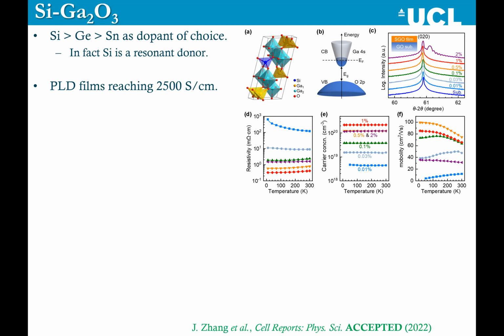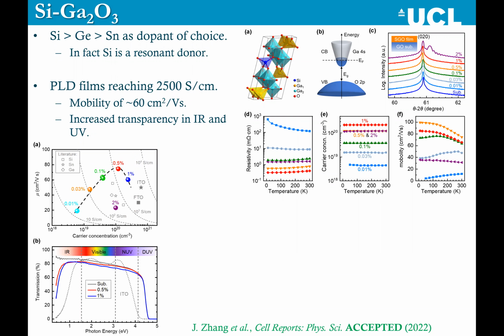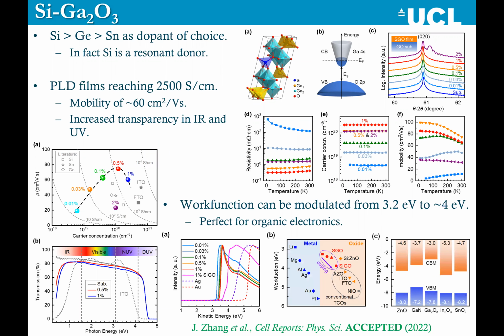But what we showed using our same band structure analysis is that the silicon states sit high above the bottom of the conduction band, and they do not mix with the bottom of the conduction band, meaning that silicon actually acts just like those transition metal dopants did in those other systems that I was showing. So again, nice, lots of transparency in the IR, same type of mechanism.